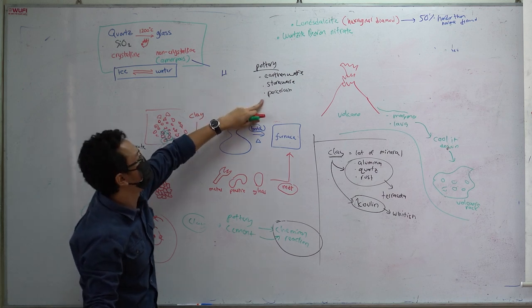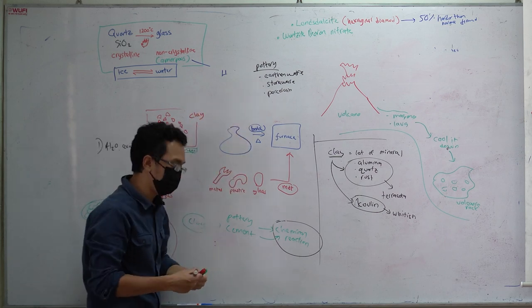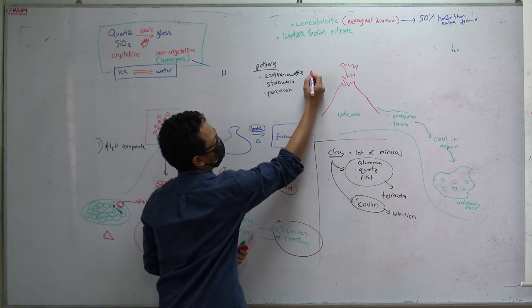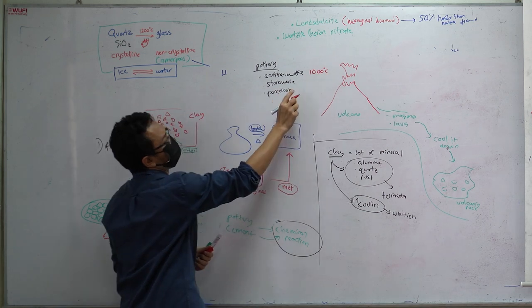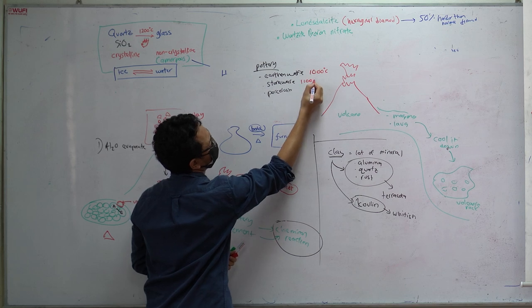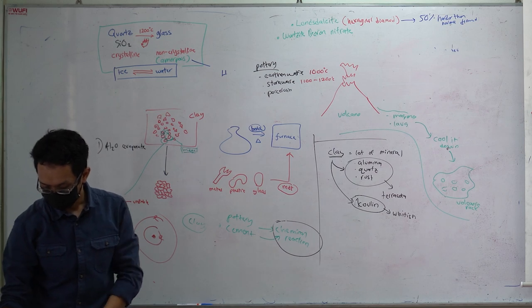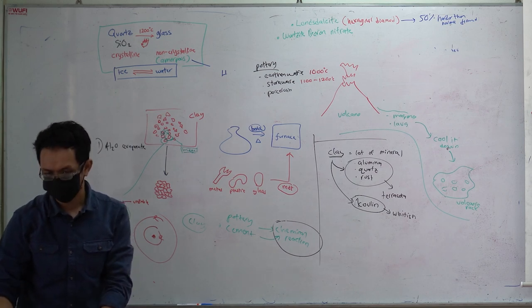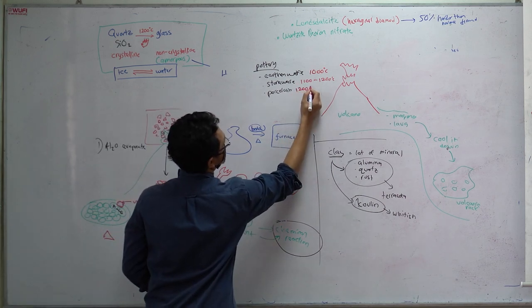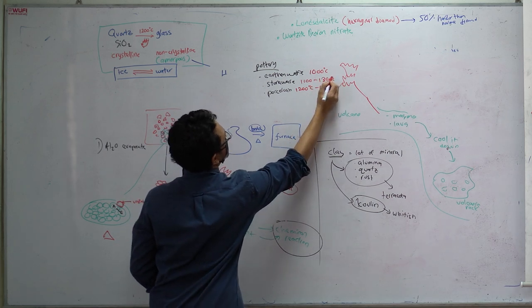The difference between these three is that, to make earthenware, you need a temperature that is lower than the rest. Normally for earthenware, you need a temperature around 1000 Celsius. Stoneware, you need around 1200 Celsius or so, and for porcelain normally beyond that. For porcelain, you need a temperature around 1300 to 1400 Celsius. So that's the difference.